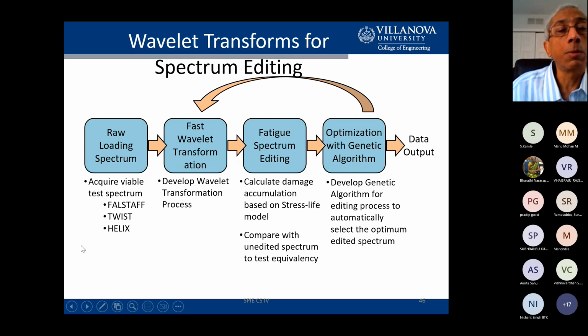So this is our approach. If you've got a particular spectrum that you want to scrunch down, edit, then we implement something called a fast wavelet transform, and then once we transform or edited the spectrum, we calculate the damage. You can do it a couple of different ways, using something called a stress life model, or you could use crack propagation ideas. We've done both. And from that, you predict the life or the damage. And if the damage doesn't match up with that imposed by the full spectrum, then you go back and change your parameters of the fast wavelet transform. And then you optimize the choice of the fast wavelet transform parameters by doing the cyclic approach. And so we use a genetic algorithm for doing that optimization.